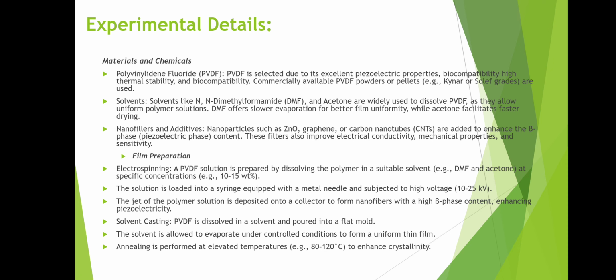When we talk about nanofillers and additives, the nanoparticles we are using are such as zinc oxide, graphene, or carbon nanotubes. We add these nanofillers to enhance the beta phase, as a result of which the piezoelectric effect will be increased. These fillers also improve the electrical conductivity, mechanical properties, and sensitivity. In film preparation, we use electrospinning, and the PVDF solution is prepared by dissolving the polymer in a suitable solvent, as I have told you earlier, DMF and acetone, at a specific concentration like 10 to 15 percent weight. The solution is then loaded into a syringe equipped with a metal needle and subjected to a high voltage, 10 to 25 kilovolts, and the jet of polymer solution is deposited onto a collector to form nanofibers with high beta phase content.